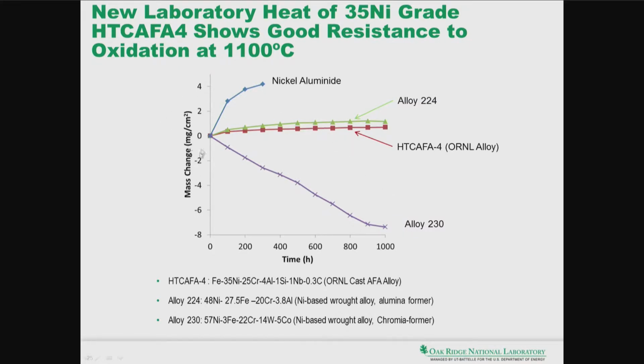What we are showing here is the oxidation mass change as a function of, again, the time at 1100 C. And the nickel aluminides actually don't do as good as the alloy 224, which, I just want to show you, has about 48 nickel and 3.8 aluminum and some iron and chromium, which is actually a nickel-based wrought alumina-forming alloy. And the HTCAFA-4, which is an ORNL cast AFA alloy, which is also an alumina-former.